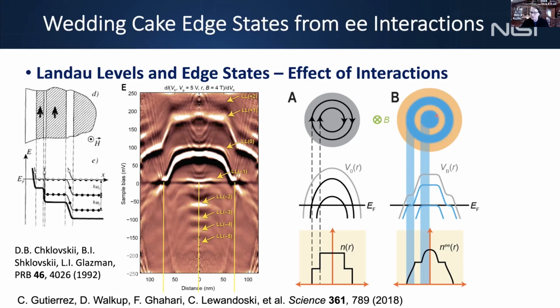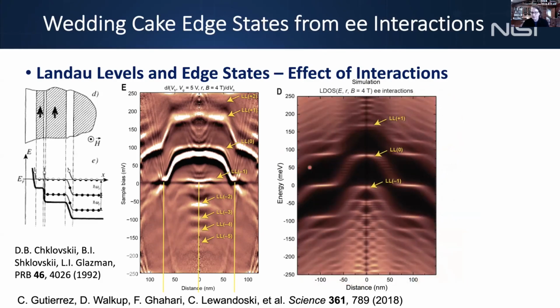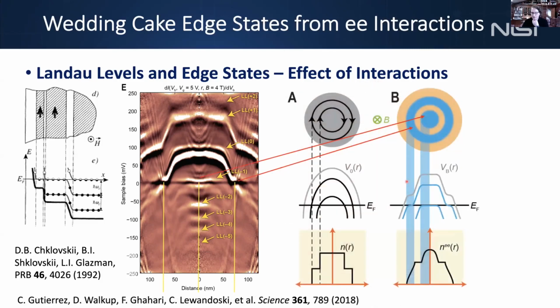But you end up with these compressible rings, compressible disks, when the Landau levels are at the Fermi level. So here's a compressible disk, here's a compressible ring. And you can show that in the calculations. If you take electron interactions into account, you can reproduce this kind of wedding cake structure. But what I want to show you, which is a little more interesting, is that these compressible structures are Coulomb islands in themselves. So now you have an isolated Coulomb island separated by an insulating region. They're going to act as a quantum dot in their own right.